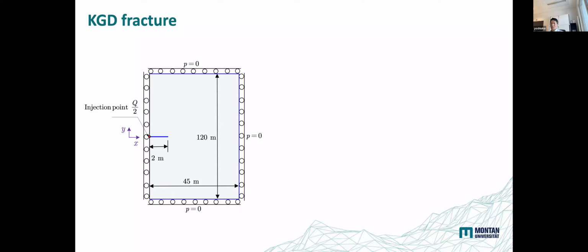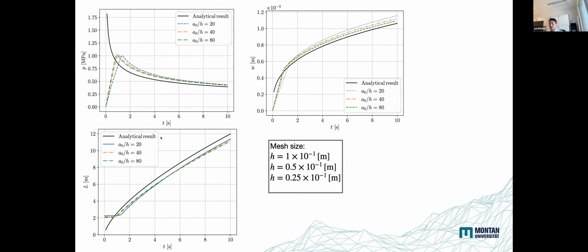So we apply our model to the KGD fracture. Okay, so plane strain, and we have an injection point here. This is just half of the domain, and we have a line crack. And here is our verification result. Sorry, this is the pressure response, and this is the fracture aperture at the injection point with time. The x-axis is time, and then this is the fracture length. And we tested our model with different element sizes. So A naught is the half length of the fracture, and H is the element size.